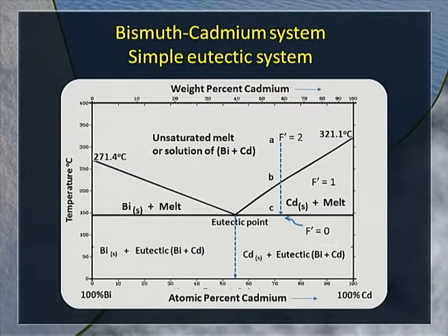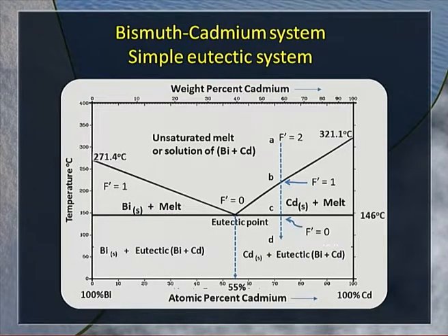We had cadmium and the melt. Now bismuth also makes its appearance. Because of that, we lose the degree of freedom that we had. Ultimately, we get the value for degrees of freedom 0. The system becomes invariant. There is a temperature halt till the melt completely disappears. And further cooling is possible when we have only solids present in the system. So it is possible for us to explain the phase diagrams based on the general system that we had seen last time.